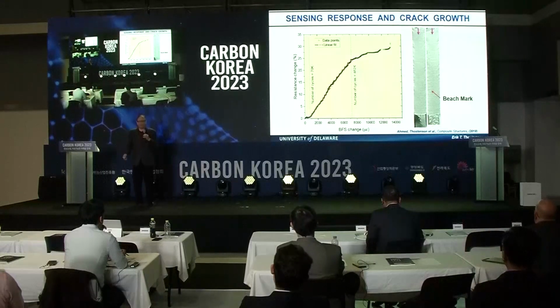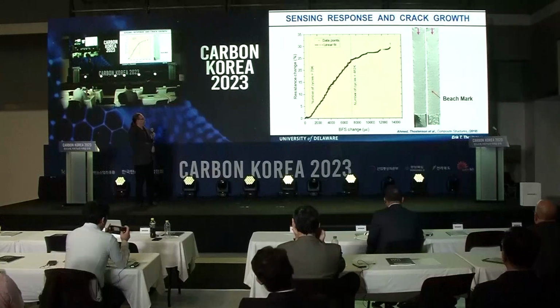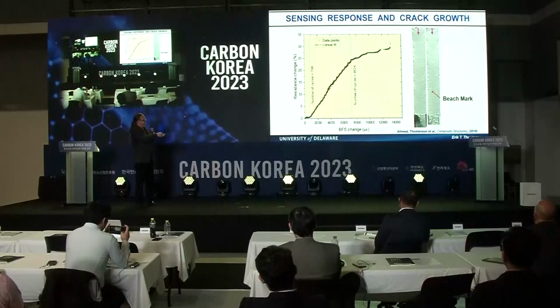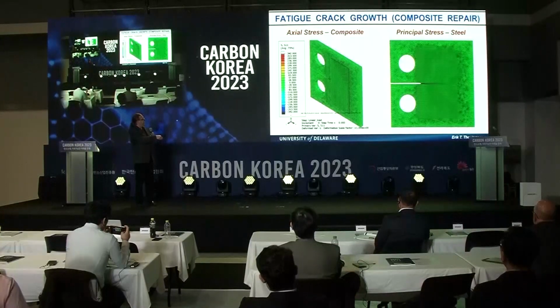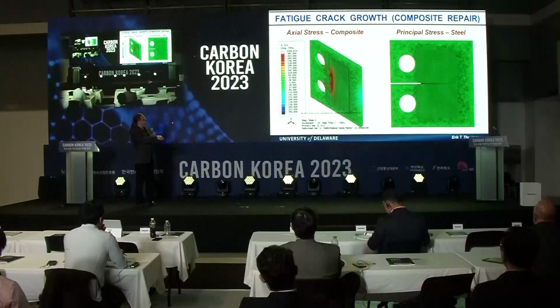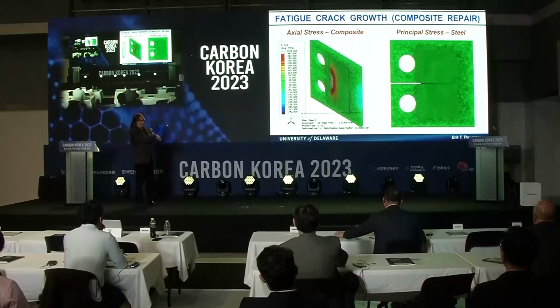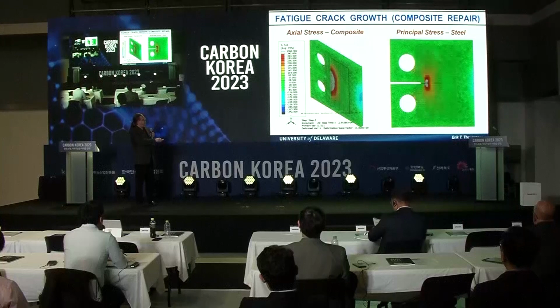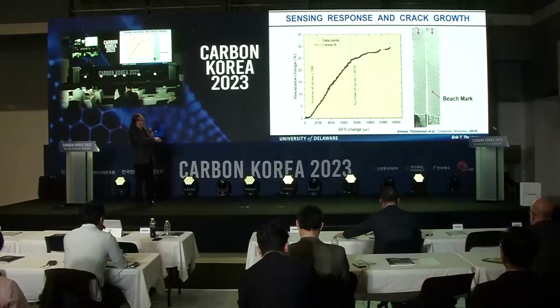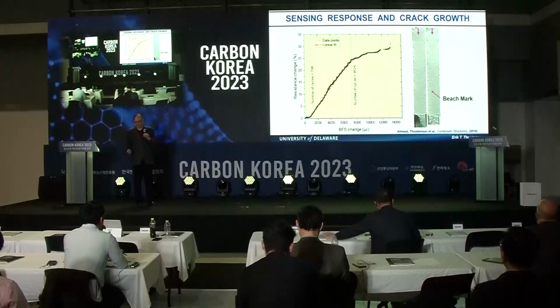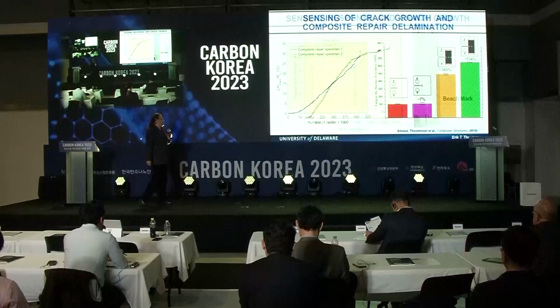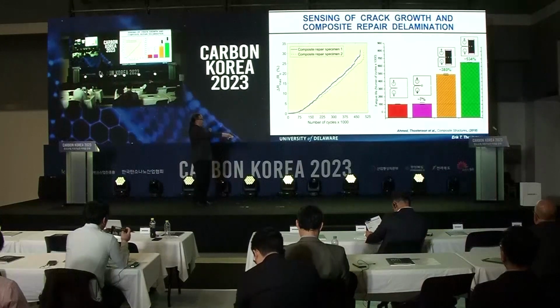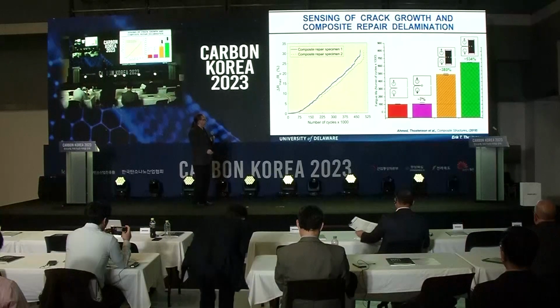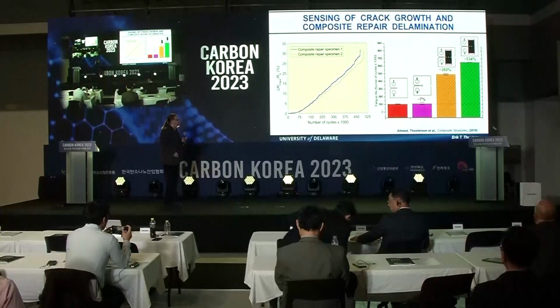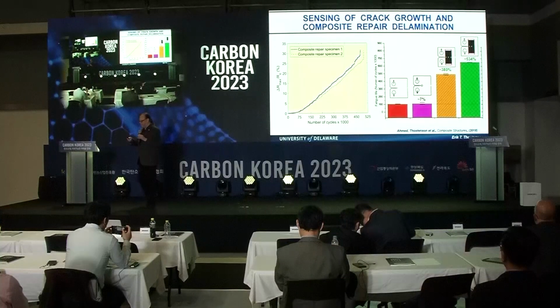And we've done quite a bit of work, both fractography, looking at the crack position, and also we can measure what's called the back face strain. And what you see in the videos is that the backside of the specimen is in compression, so we have a strain gauge right in that area, and we're able to track that back face strain. And where you see it start to deviate, we actually fatigued the strain gauge. But we're able to track the motion of that crack and the length of that crack very accurately, not only using the back face strain gauge, but also looking at the fracture surface.